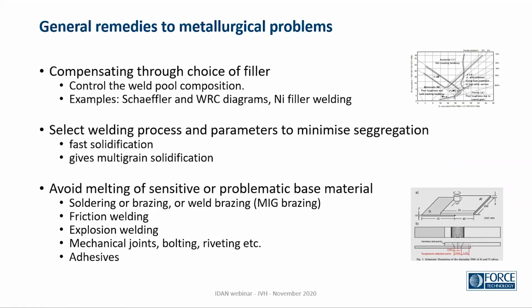General remedies to the metallurgical problems. Some problems might be solved by choice of filler material, to throw the weld pool composition away from the risk of having intermetallics or solidification cracking or what the problem might be. A well-known example of that is welding stainless steel using the Schaeffler diagram. It's a small one over here. We will return to it shortly. Or it could be using a nickel filler for the welding. Nickel is very much able to contain other metals and impurities, and by that avoid having problems.